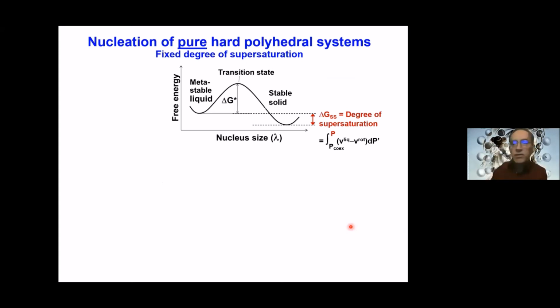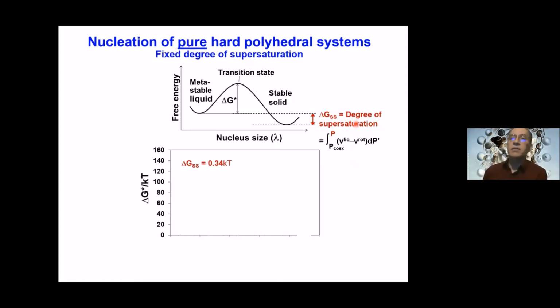So let me just briefly give you a flavor of what we are doing. You can measure rates, or you can also measure, as a surrogate for rates, this free energy barrier. This is free energy as a function of, say, the nucleus size of the solid phase. As you go from the metastable liquid to the stable solid, the height of this barrier will tell you something about the kinetics. If it's large, that means that there's more difficulty in going from here to there. Now you can compare these kinetic rates by comparing systems for the same driving force, and the driving force is this degree of supersaturation.